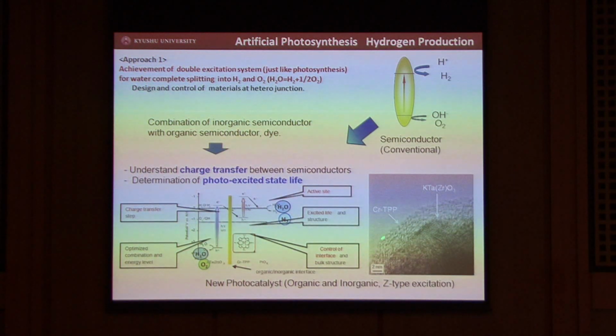This is our preliminary prepared catalyst. We use KTaO3 as the center, covered with chromium tetraphenyl porphyrins. By using the excited electron passed to the chromium tetraphenyl porphyrins, we can successfully achieve this kind of Z-shape excitation of the electrons.